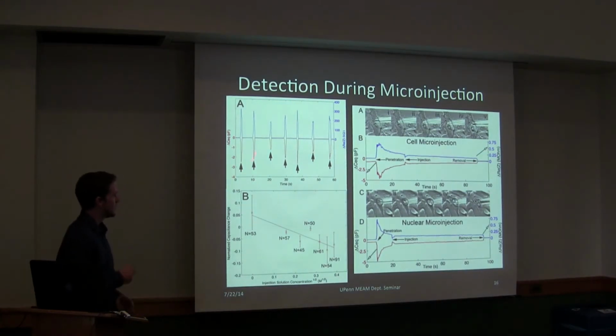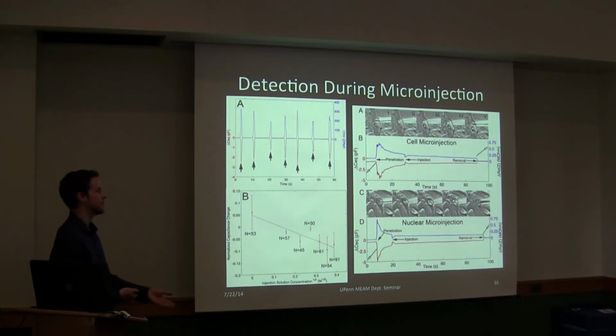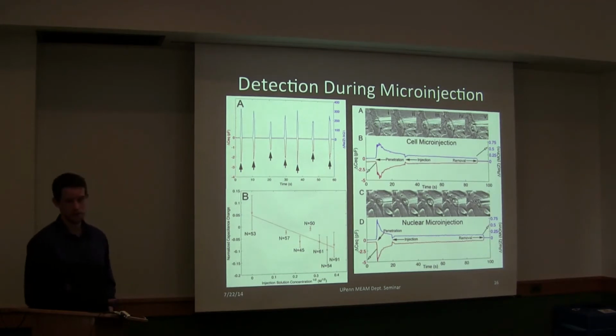So with that, we did some studies under 2 different modes of injection. So we have this plot here. The red curve and this lower axis is the equivalent capacitance, which is essentially the inverse of the imaginary impedance. We work with capacitance because electrochemically, there are known relationships between things like the solution composition and the capacitance, so it's very easy to work with and easy to analyze. And then the top blue curve is the real part of the impedance. And each of these arrows corresponds to the injection of a single cell under a continuous flow condition.